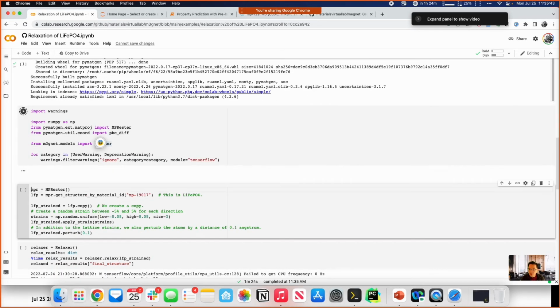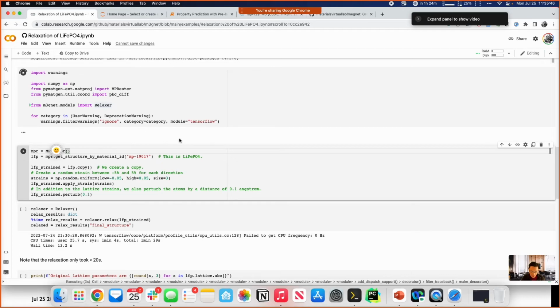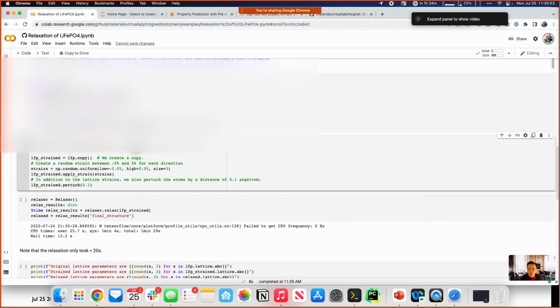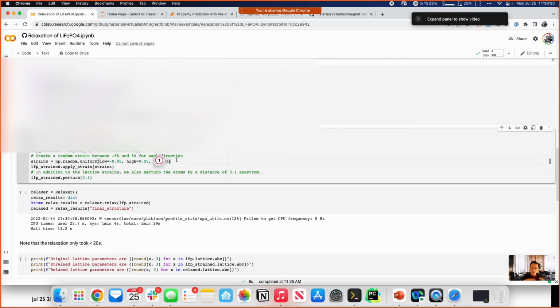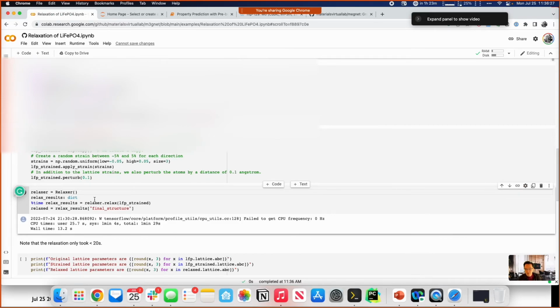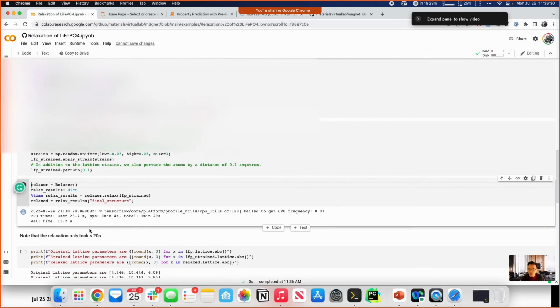Okay, that install is done. So now we can do these imports. And again, for MPRester, you actually need your API key. You can use the one that I gave earlier. If you go to the Materials Project, you search for lithium iron phosphate. The Materials Project ID is actually mp-19017. So we are going to get the LFP structure from there. And what I show here is that I'm going to artificially strain the LFP structure by some arbitrary strain of up to 5%. And I'm going to apply the strain to the structure, and I'm going to perturb the atomic positions as well. This is just to generate some perturbed structure that we are going to do structural relaxations on. If you do this, it is very fast. You should get it within a few seconds.